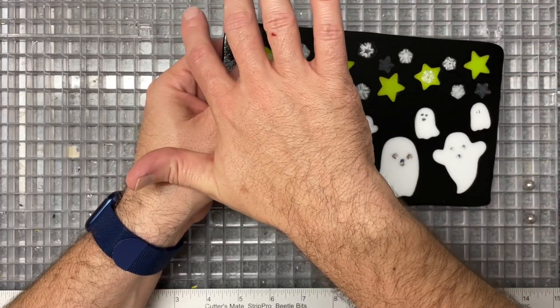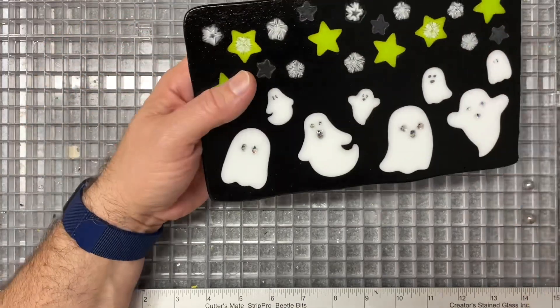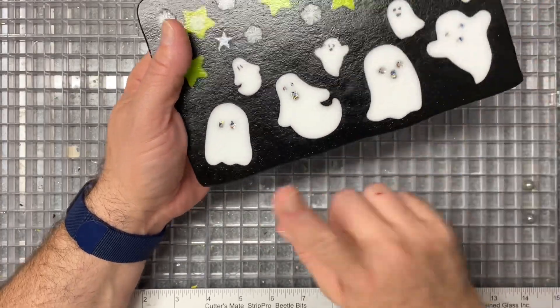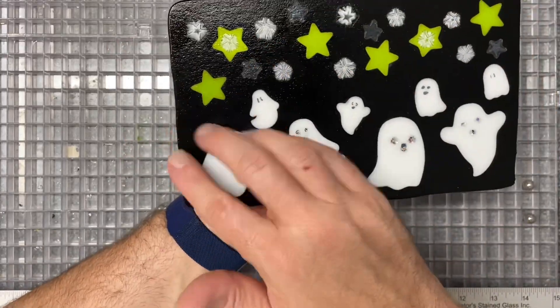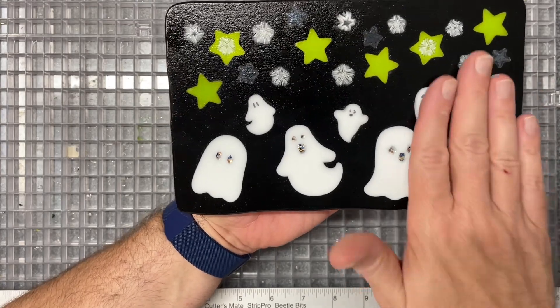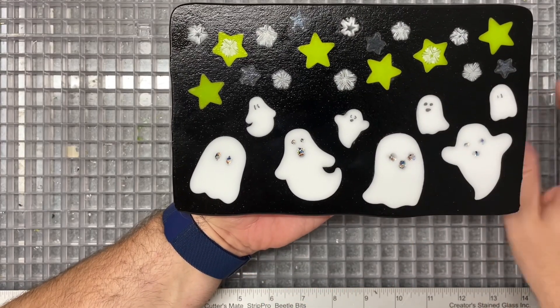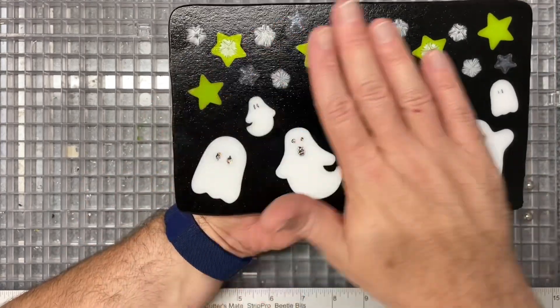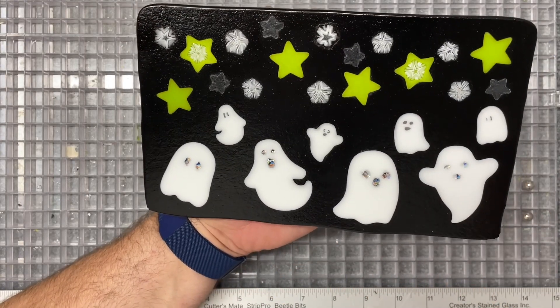It's not perfectly flat, and this part I actually need to grind down because I'm going to slump this over a half-dome shape so that it becomes a self-stander — it needs to sit flat. I need to flatten the bottom edge; the top and sides being a little organic is okay. I'm going to take it to the grinder, take a little bit off the sides where it's a little spiky, then make sure it's really clean, dust it with clear powder, and put it back in the kiln for another full fuse. That's going to totally shine up the back and really make this pop, and then I'll slump it.